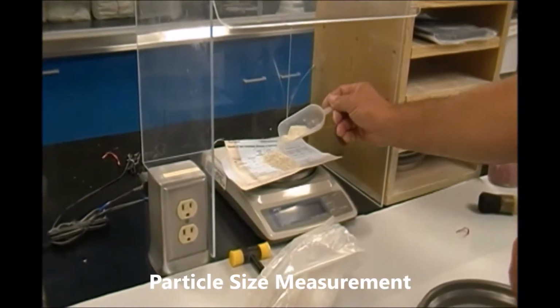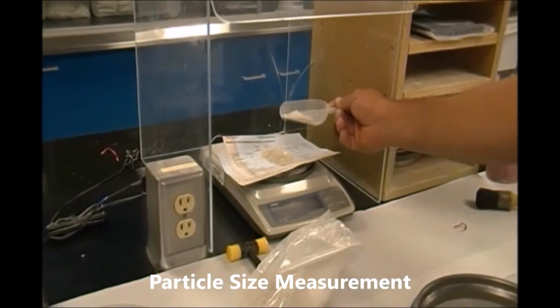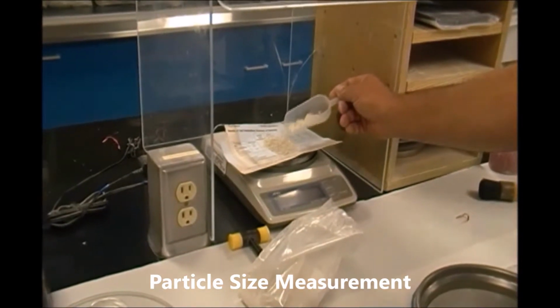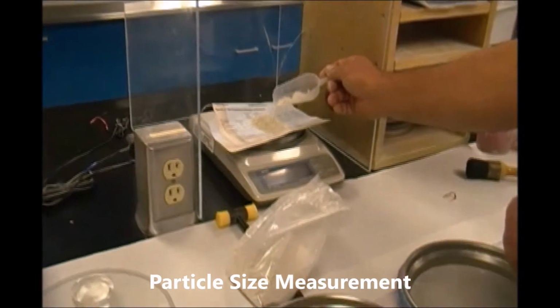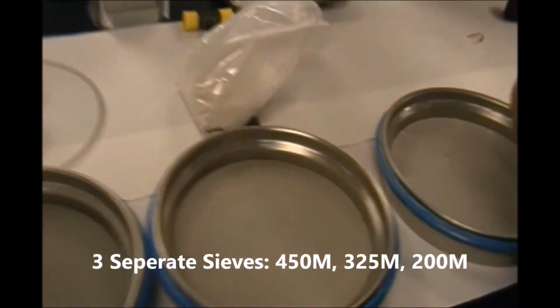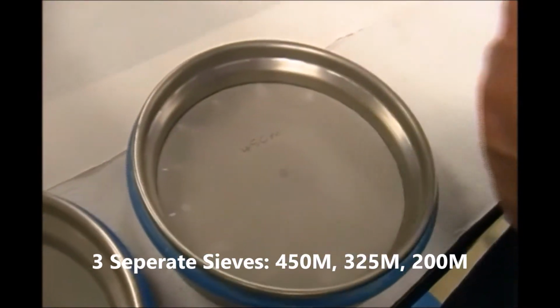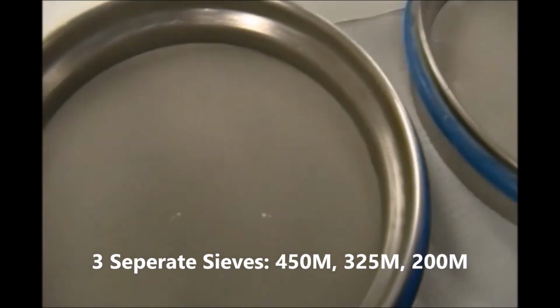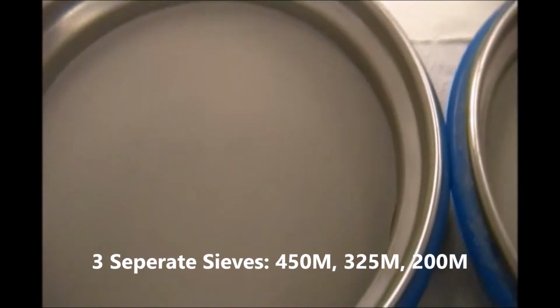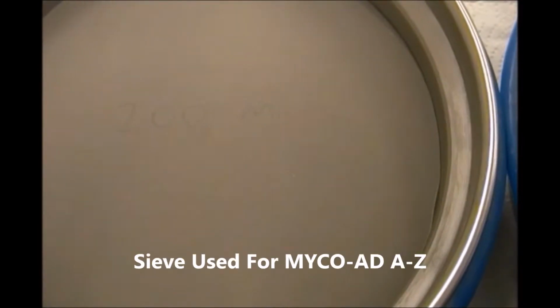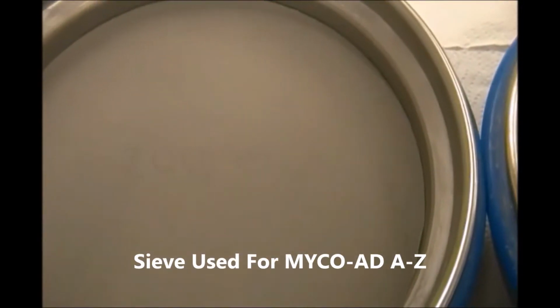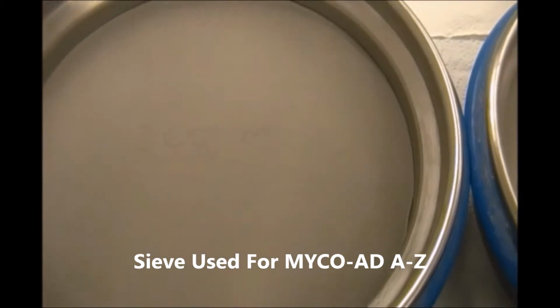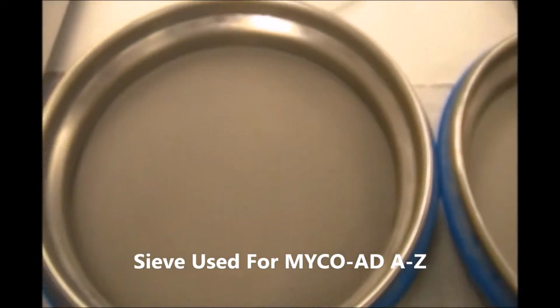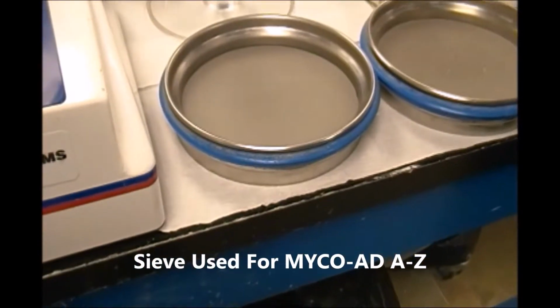In this area of the laboratory is where we measure particle size. What we will do is measure out 10 grams of product. The product will then be put into one of these sieves, which is used for a sieve analysis test. Each sieve is a different size. You'll notice here that we have a 450 mesh screen, 325 mesh screen, and a 200 mesh screen. The 325 mesh screen is used for MycoAD, and the 200 mesh screen is used for MycoAD AZ. In this trial, we'll be using the 200 mesh screen for MycoAD AZ.